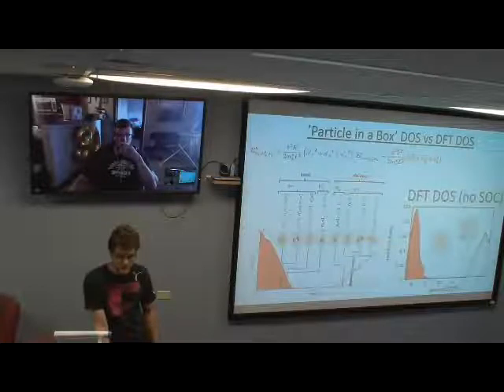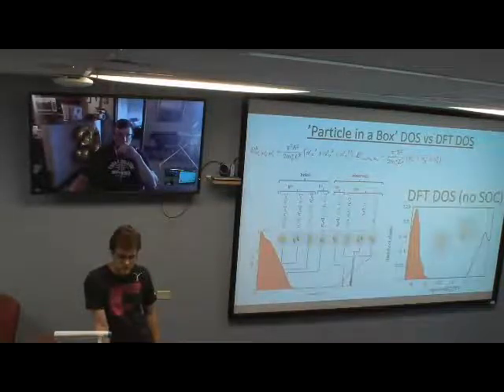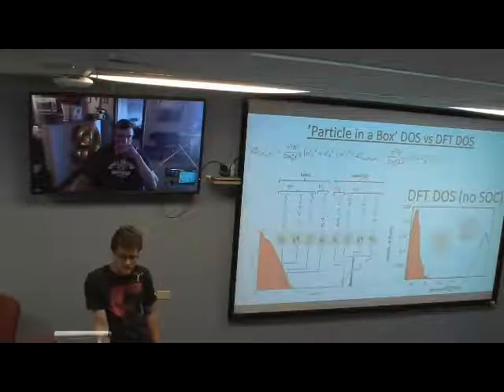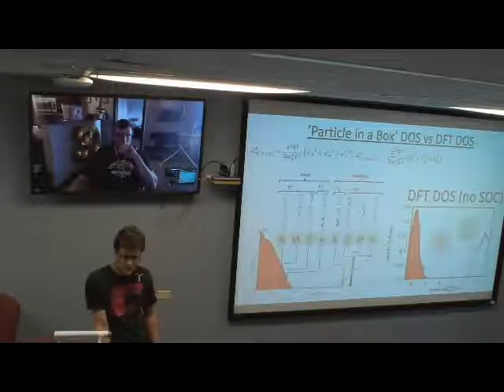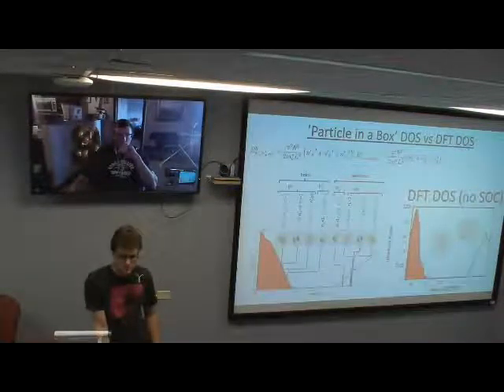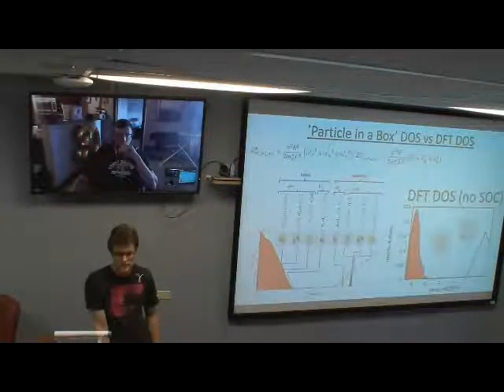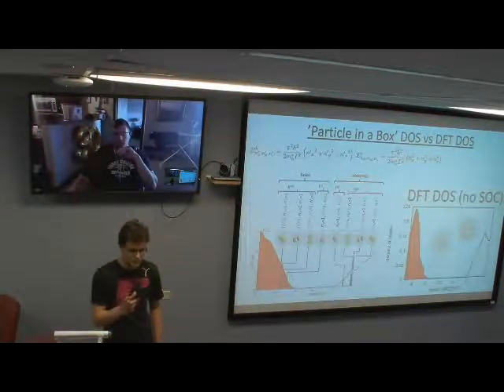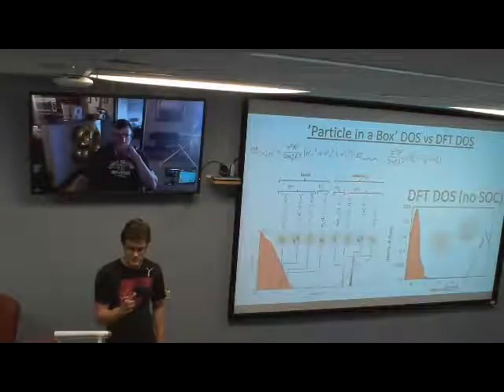So first you probably can think about correcting this solution, going to a little bit heavier mathematical part, because the solution for the finite box is not as simple as for the infinite box. But first of all, you probably can play with the parameter of the height for your potential. Go to the finite size potential, with some height which allows tunneling of the wave function outside the box, even if your energy is lower than the potential. Mm-hmm. I think we kind of artificially account for that. The edge lengths aren't the same for each side, so you get...